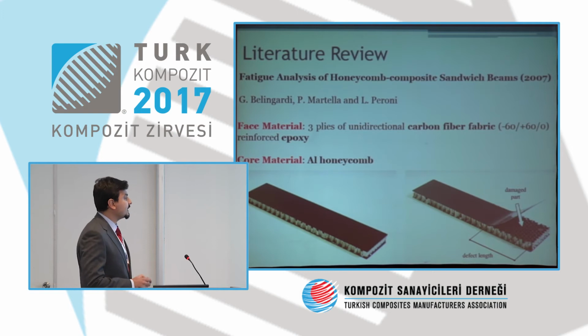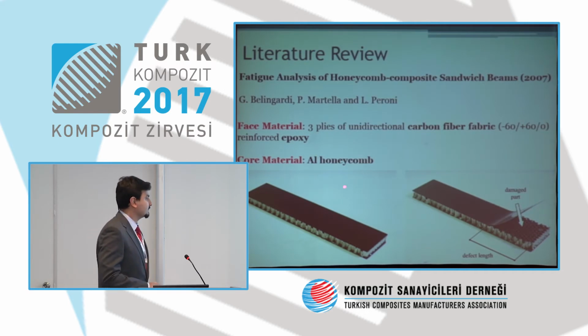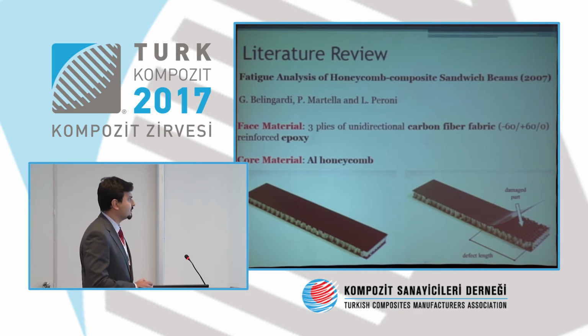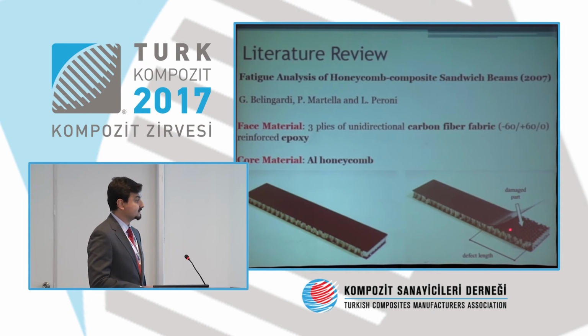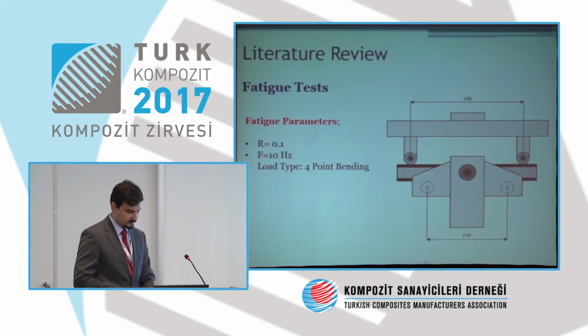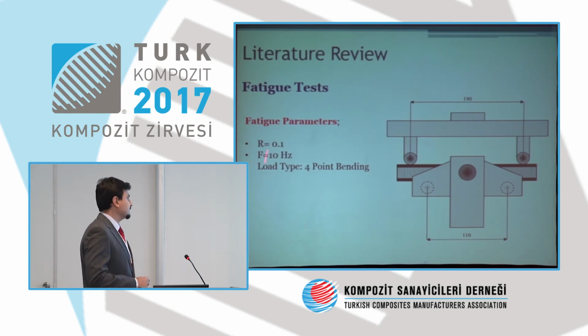And the last one is actually the closest one to our study, because they use carbon fiber fabric as face material at this orientation, and aluminum honeycomb core. It's published in Composites Part A, I guess: fatigue analysis of honeycomb composite sandwich beams. They used two different specimens. First the undamaged specimen, and then they applied the fatigue loads on the damaged specimen. These are their fatigue parameters. They chose the high frequency, 10 hertz, and load type 4-point bending, and R is 0.1 again.